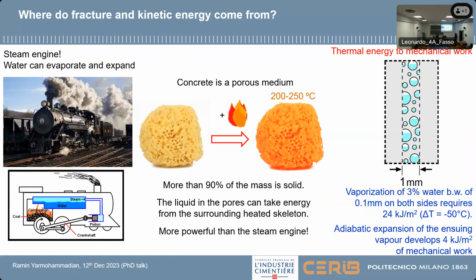So we have a porous medium, which is concrete, and these pores can be filled or semi-filled with water. And then we have 90% of the mass, which is solid. And these 90%, when heated up to 200 or 250 degrees Celsius, can instantly provide energy to the water which is stored in the small pores inside. So in my opinion, it's even more powerful than a steam engine.